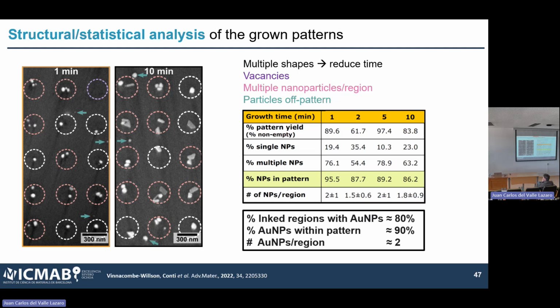And yeah, it's not easy, as I said, mainly because of the characterization. So we don't have the TEM tool where you can really look at the details of the particle. And with an SEM, when you go below 20 nanometers, it's complicated to tell if it's a sphere, if it's a cube, it's really, really hard. And so that is actually right now the main problem that we need to solve. I think that if we crack the characterization and understand what we are seeing, then we are on the good track to actually make this interesting in terms of growing identical particles.